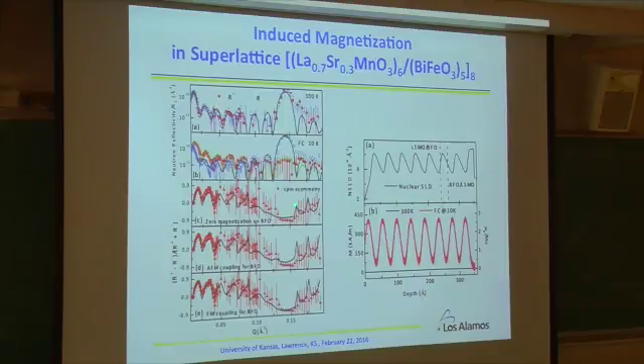So here we check, for example, room temperature. If you look at the spin up, spin down, it's just red and blue. They overlap with each other. That means across the interface, there's no magnetic property. However, if you go to, for example, 10 Kelvin or so, you see the difference. Here is the raw data. At 10 Kelvin, you see obviously that kind of separation. Spin up, spin down, you see the difference. Probably you can ignore this, just look over here. This is just the magnetization as a function of depth, from the surface to the substrate.